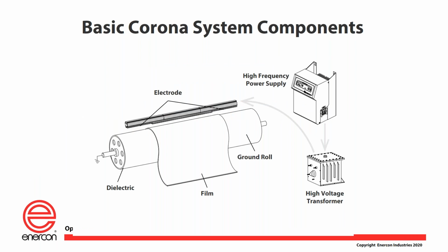So here are the basic components of a corona treater. You have a power supply, you have a high voltage transformer, which then steps up the voltage to about 10,000 volts. And in the air gap between the electrode and the ground roll, what we do is we ionize that gap with an electric field to generate a high electric field so that you can create corona. And that's basically a real simple schematic of a corona treater.